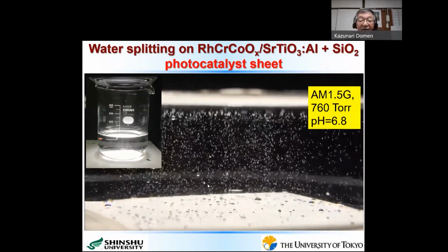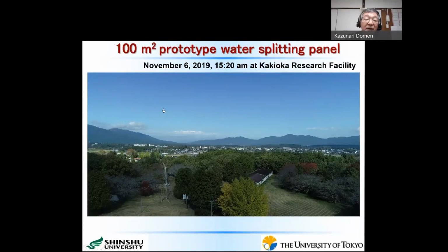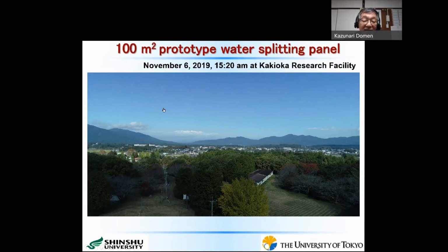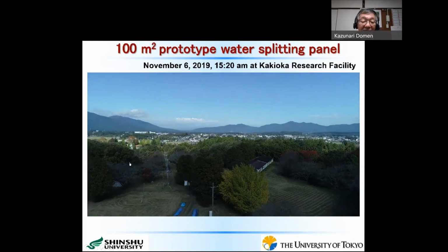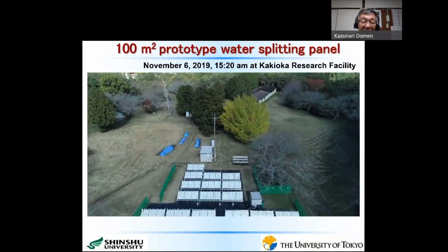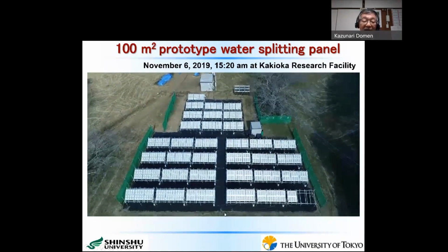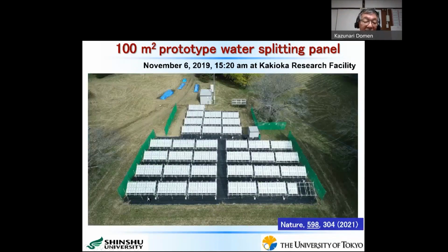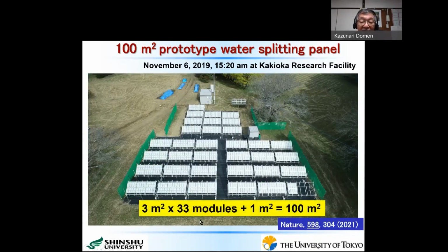included in sunlight. Then we constructed, based on this type of photocatalytic materials, a 100 square meter prototype water splitting system at the Kakioka Research Facility, that is within the University of Tokyo. As you see here, there is a small hill, and on top of this hill, there exists a little bit flat place. And here we extended our water splitting panel as shown here. Actually, these are 3 square meter modules, and then we constructed 33 modules, and here we have 1 square meter additional panel. So total light receiving area is 100 square meter.